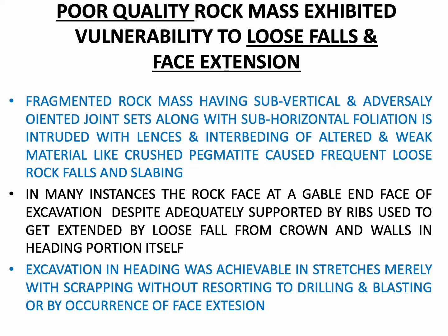So poor quality rock mass exhibited vulnerability to loose falls and face extensions. This is the background that we must keep in our mind, that the poor quality rock mass in the downstream surge gallery exhibited vulnerability to loose falls and face extension because the Jn by Jr ratio was more than 6 and was of the order of 9 to 12. The fragmented rock mass having subvertical and adversely oriented joint sets along with subhorizontal foliation is intruded with lenses and interbedding of altered and weak material like crushed pegmatite caused frequent loose rock falls and slabbing. In many instances, the rock face at the gable end face of the excavation, despite adequately supported by ribs, used to get extended by loose fall from crown and walls in heading portion itself.